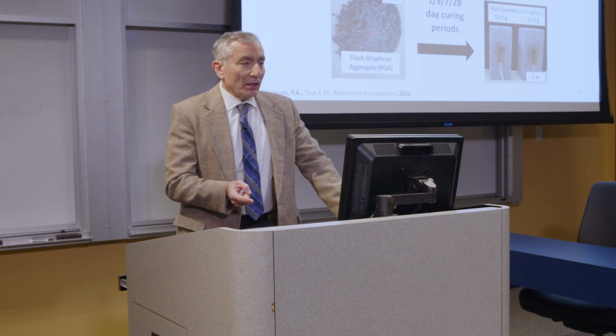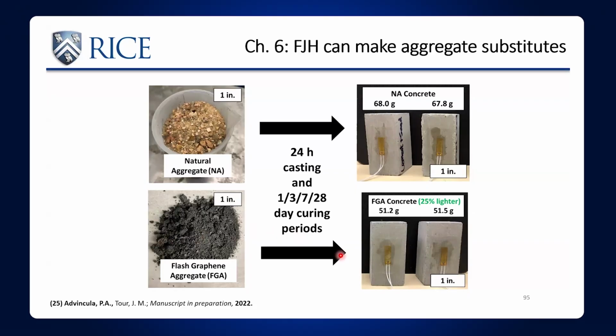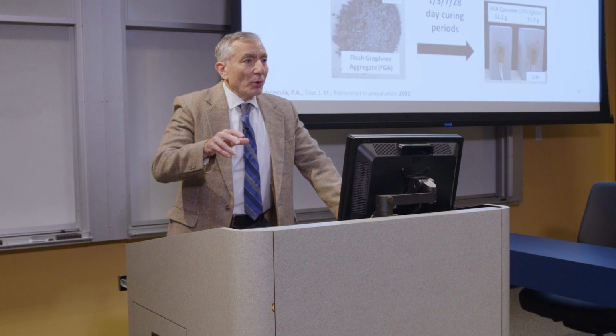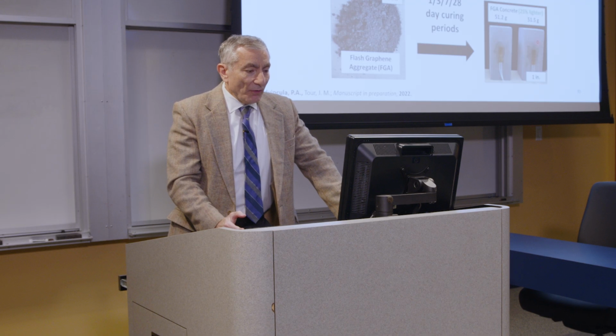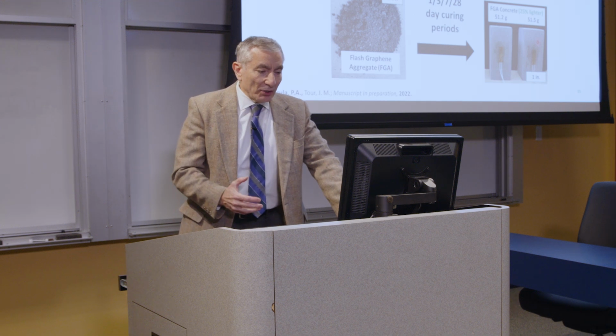He made concrete out of it. So this concrete has no rocks in it. It only has flash graphene of the same size as natural aggregate. And it's 25% lighter. You know, no surprise. I mean, carbon, if you look on a periodic table, carbon's near the top. And if you start putting in iron, calcium, silicon, all of those are going to weigh more than carbon. So this ends up being 25% lighter. So you have 25% lighter material.